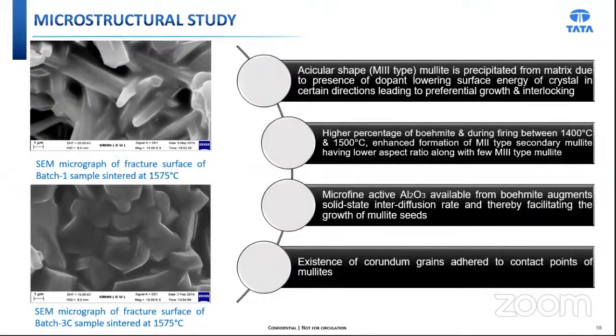With presence of dopant, some acicular M3 type mullite is observed throughout the matrix. With addition of higher percent of boehmite, and during firing at 1400 to 1500 degrees centigrade, the M2 type mullite, basically rod-like morphology, is observed in the mullite matrix with the aspect ratio, along with a few M3 type mullite having longer aspect ratio. Microfine active alumina is also available from boehmite, augmenting solid state interdiffusion from the mullite seeds. Existence of corundum grain adhered at the multi-grain junction. So corundum grain, that is basically alpha alumina, is also observed.